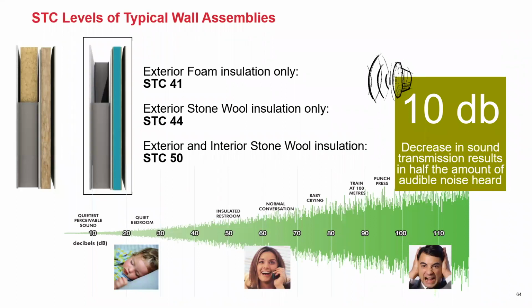So, here are typical STC levels of exterior walls. If you look at a commercial wall that has exterior foam insulation only, that might have a rating of STC 41. If you compare that to just having stone wool insulation on the outside, it's a bit higher at STC 44. If you have a combined batt insulation and semi-rigid stone wool on the outside of your wall, you can get to an STC 50.